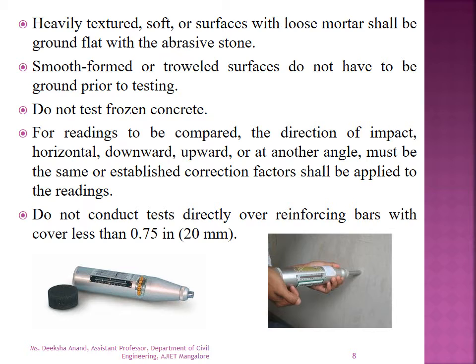The hammer, which is in contact with the surface, has a plunger and spring inside, and a scale to record the reading. This hammer should not be used on frozen concrete. It should always be used on a smooth form or trowel surface. Do not grind prior to testing and do not conduct the test directly over reinforcing bars with cover less than 0.75 in or 20 mm.